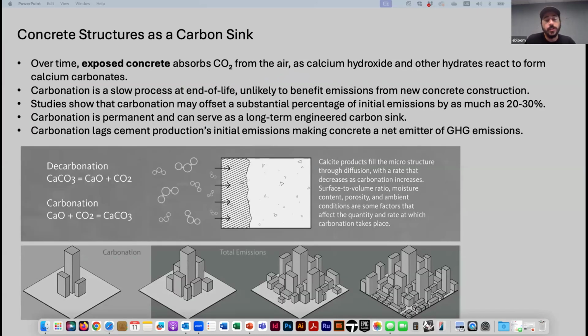And so to wrap up concrete, I think when we talk about concrete, an often overlooked blind spot is concrete's potential as a permanent long-term engineered carbon sink. Through carbonation, exposed concrete surfaces will reabsorb atmospheric CO2 through diffusion, and then that starts to fill in the microstructure of the exposed concrete with calcite products. The diffusion rates depend on a number of ambient conditions, but ultimately carbonation is a very, very slow process. And LCAs, which use 50 or 100-year time horizons, struggle with how to credit those removals in time periods beyond that. A number of studies do point out, though, that LCAs that exclude the carbonation benefits of concrete might be understating them by as much as 20–30% of initial emissions.